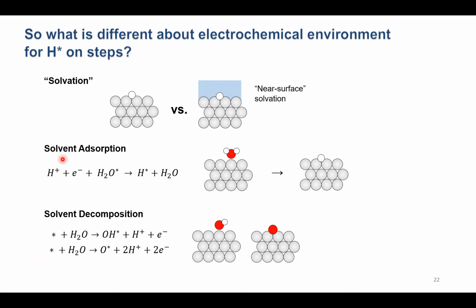The first is that we have to consider solvent adsorption. Maybe water binds very strongly to the platinum step edges, and so hydrogen, to adsorb, needs to displace that water. That would then affect the adsorption energy that we measure experimentally for hydrogen in the electrochemical environment. It would be convoluted with the adsorption energy of water. And we should also consider solvent decomposition. When we measure a CV in an aqueous electrolyte, we see an adsorption peak, but we cannot determine whether that adsorption peak is coming from hydrogen, hydroxide, or oxygen, basically any decomposition product from water, from the voltammetry alone. And so we also have to consider that maybe that peak involves hydroxide adsorption or oxygen adsorption.